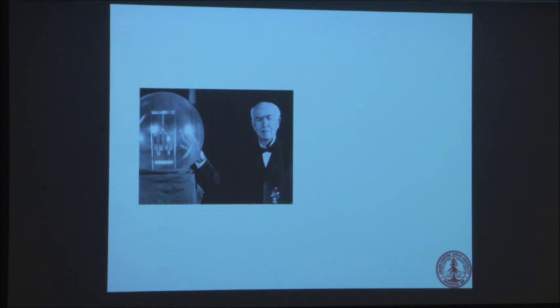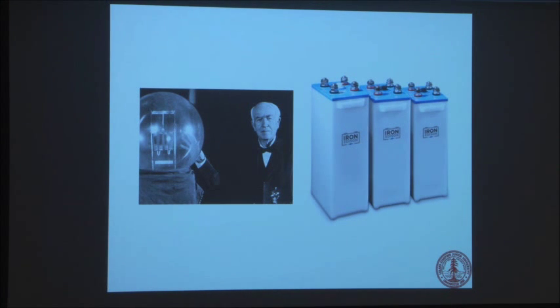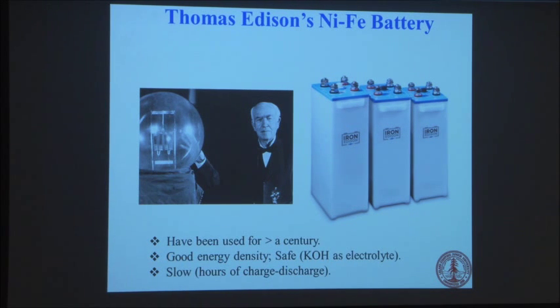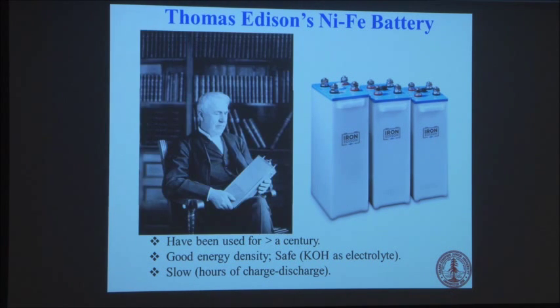Everybody knows Thomas Edison, who invented the light bulb, but he also invented batteries. The battery he invented was a nickel-iron battery. One side is nickel, one side is iron, and you have potassium hydroxide as the electrolyte, and you can basically oxidize or reduce nickel, and then oxidize or reduce iron, and make a battery. It's been used for more than 100 years. It's good, the energy density is good, and it's safe, since it uses water and KOH as electrolyte, but the charge and discharge has been very slow. Here's a photo of him holding his battery more than 100 years ago.